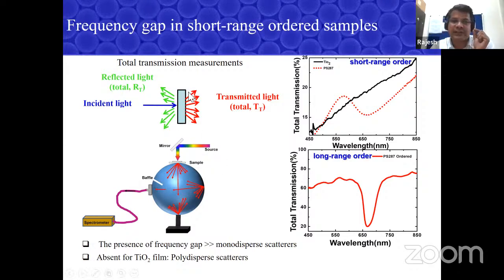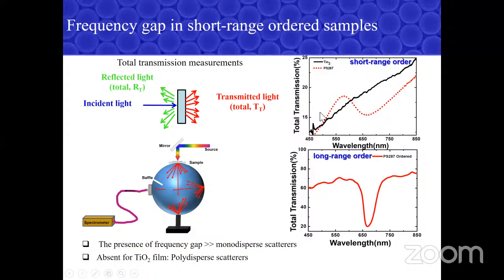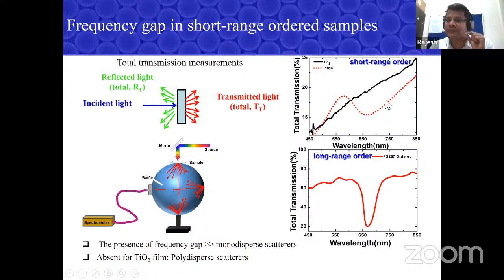So to collect all that transmitted light, we use a system called an integrating sphere. Basically, you have a sample here, it impinges the light, it transmits all the light, and it gets multiply scattered inside the sphere, and finally it reaches the detector. So this is a result of our measurements. When you don't have a short range order, the black curve, the transmission decreases with wavelength as expected. But when we measured our sample, what was really surprising to us is that it shows a dip in transmission just after 650 nanometer.